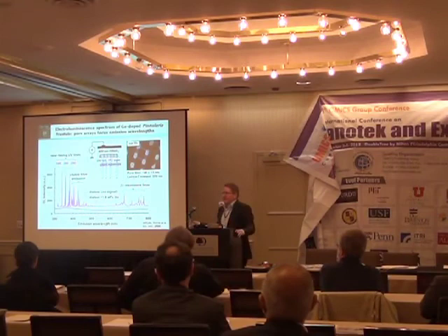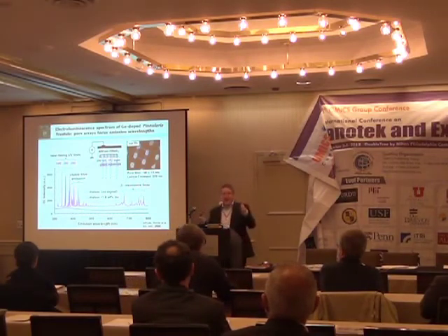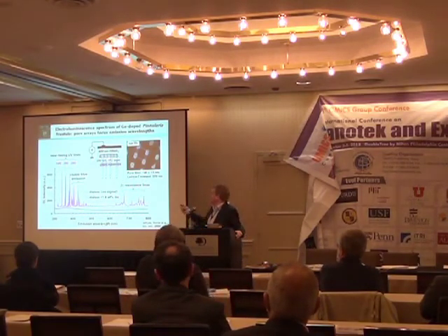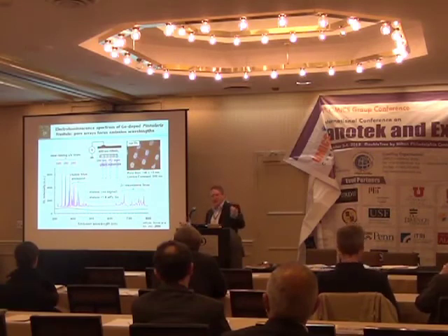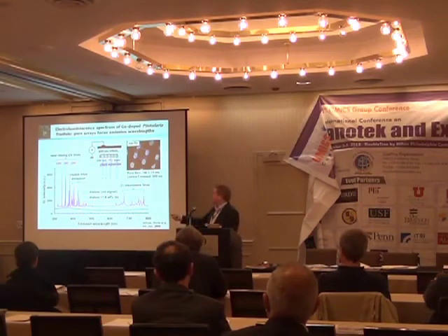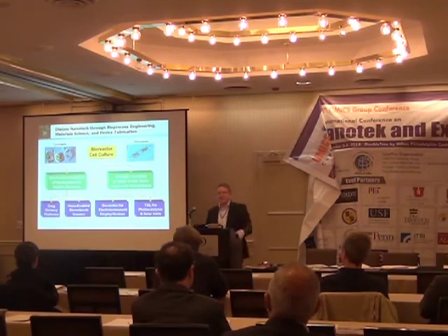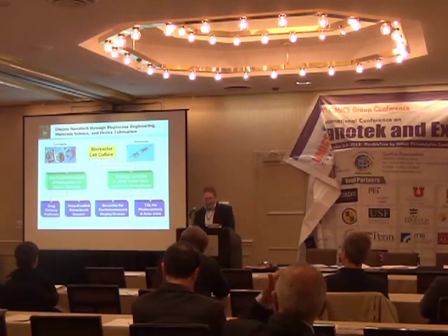And I can't go into the details here, but we've done some other photonic crystal calculations, based on the pitch of the pores and the lattice constant, that these are nominally predicted outcoupled wavelengths that you get as a result of this nanostructure. And it's not perfect here since this is a biologically produced organism. It's not producing a single lasing line, but it's showing about 3 primary ones here. So that's an example of one sort of device that we can make.